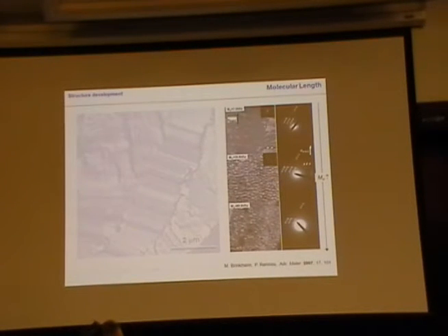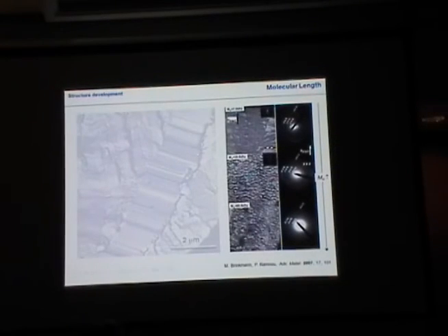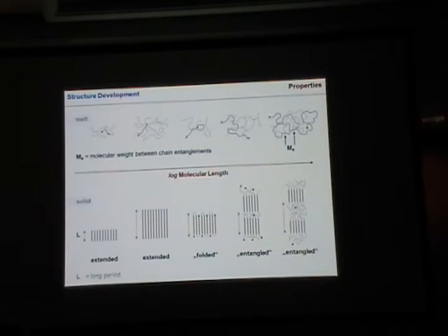Here you have a crystal. One molecule stretches from one side to the other. Here you have the smaller polyethylene crystallizing. So you have phase separation depending on the chain length. This is different than when you increase the length. Once you go to higher molecular weights, you get the semi-crystalline microstructure of amorphous phase. So the amorphous phase is less dense. And it gets more and more messy the higher the molecular weight.